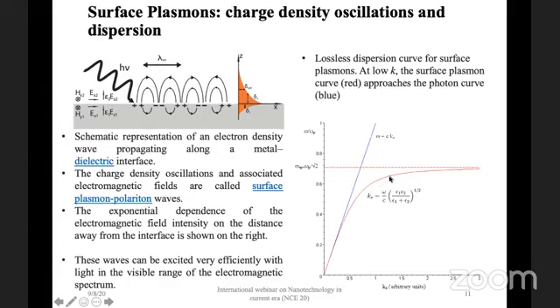Now that's one of the issues. We need to make these plasmons interact with the light. So we need to have some kind of structures which can add some momentum to these plasmons. Or we need to shift the light dispersion curve so that it can cut the plasmon dispersion curve to make it interact with that light. That can be done by using either a simple prism or gratings. So we can add some momentum to the light so that it can cut and interact with the plasmons, or it can excite the plasmons.